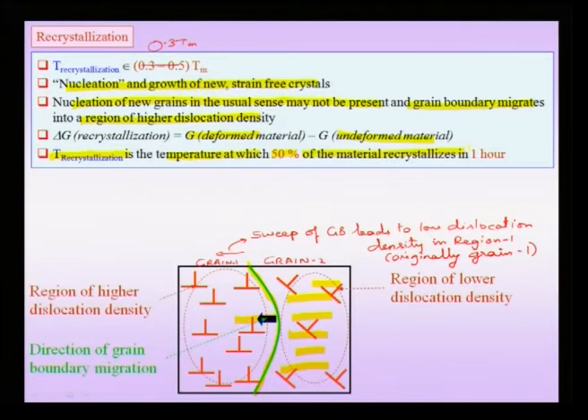We are not waiting for infinity, we are not talking about instantaneous recrystallization of the entire material, but we are saying that 50% of the material, that means 50% of the stored energy, needs to be reduced, and this needs to take place within an hour. So therefore, if I keep a material at the recrystallization temperature for 1 hour, then I can assume that 50% of my material will be recrystallized and it will be good enough to be cold worked again.